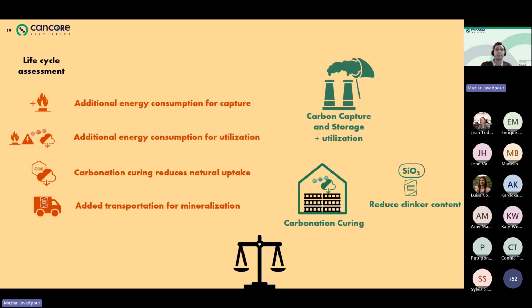Now, in our life cycle assessment, we focus on 4 key areas for carbon capture and utilization: the added energy consumption, the added energy for utilization of this CO2, the natural uptake reduction that happens once we do carbonation curing, and the added transportation. And then we put them all on one side of the scale, and we put the benefits that we get from carbon capture and from carbonation curing, the increased uptake, and the reduction in clinker content on the other side of the scale, and just see what goes on here, right?